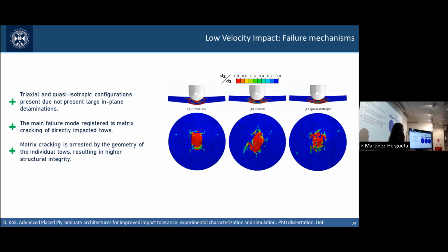Together with the experiments, we also analyzed the response numerically. We couldn't find any fiber failure for low velocity impact. And the main failure modes that we characterized were matrix cracking of the directly impacted tow, and then tow debonding as we were moving away from that impacted tow. So this really makes us think that the undulations, acting as crack arrestors quasi-statically, also have a similar effect under low velocity impact.